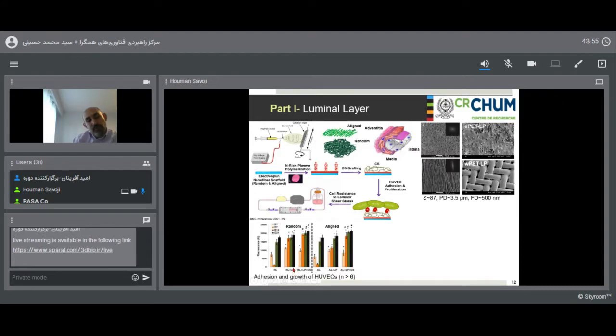Once the scaffolds are coated with the plasma polymerized coating and the chondroitin sulfate, what we saw is that the cells are really happy. They attach on day one, and they grow through the culture time until after 21 days. And on the bioactivated surfaces, they really like the bioactivated coating. They really promoted cell adhesion and growth.